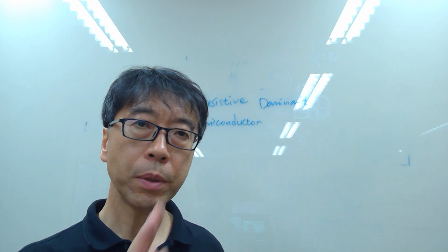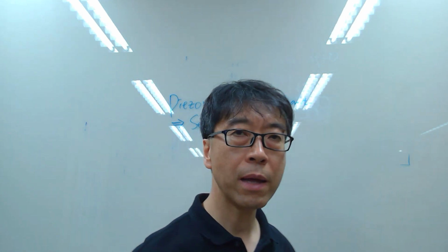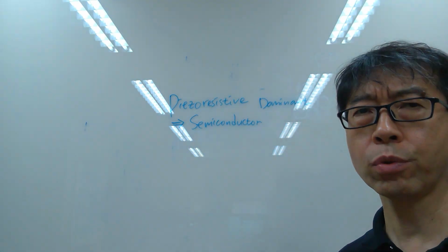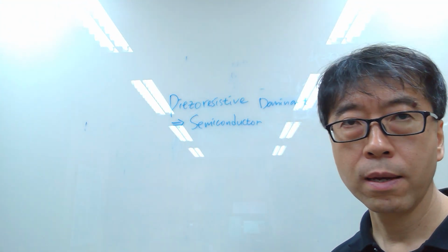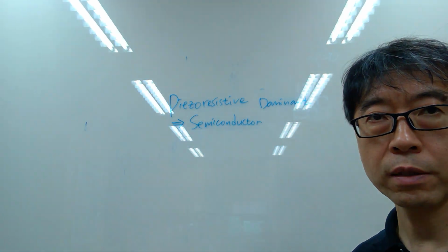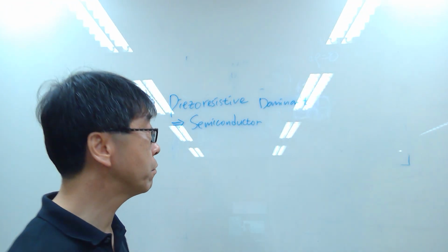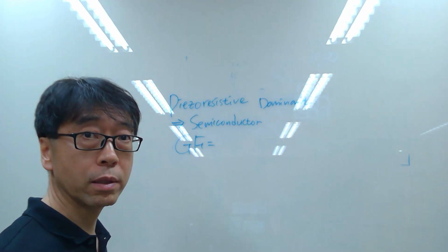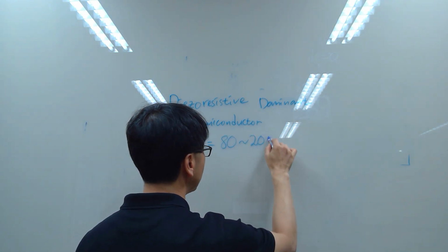Then you can come up with p-type material, you can come up with n-type material, and you see that depending upon whether you have a p-type or n-type material, you'll have totally different result of this piezoresistive effect affected by the direction of stress. And that's a very, very interesting effect indeed. And what's more impressive in this case is that the gauge factor you can achieve will skyrocket. It will go up to at least 80 or even 200.